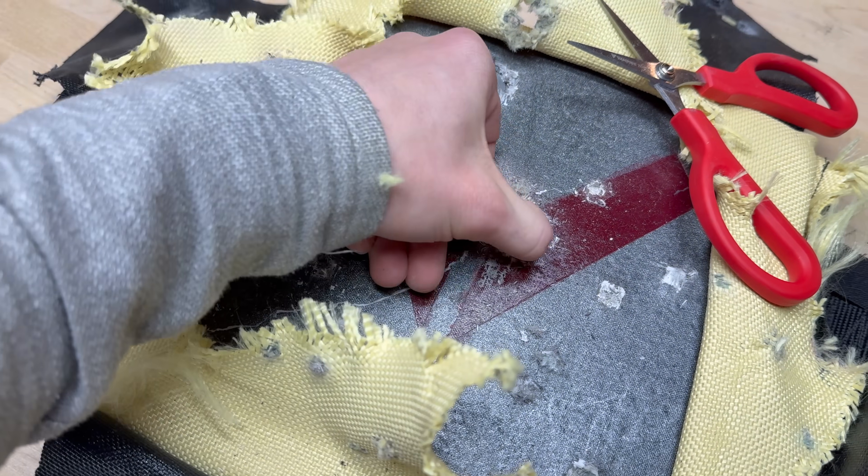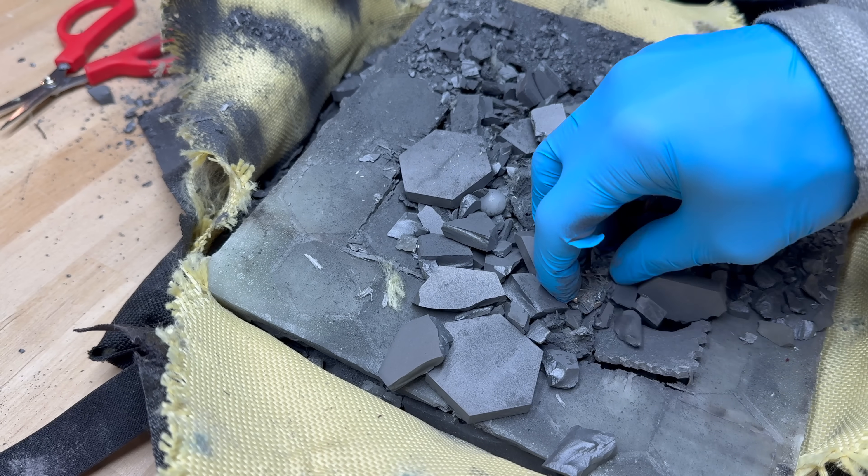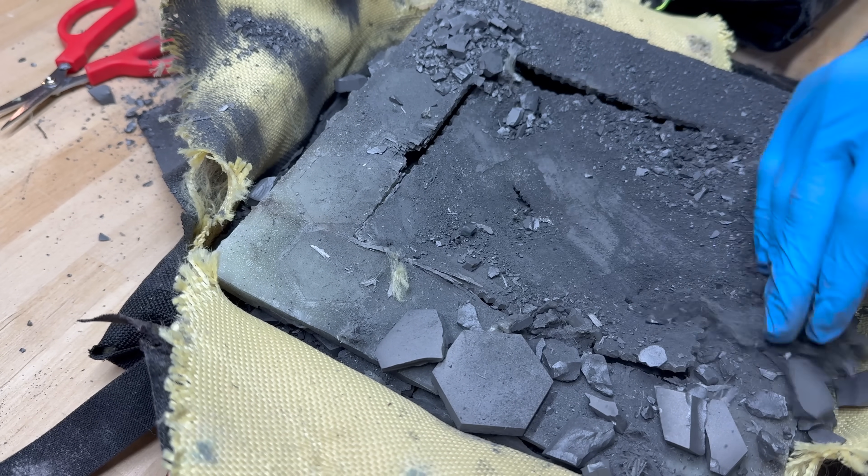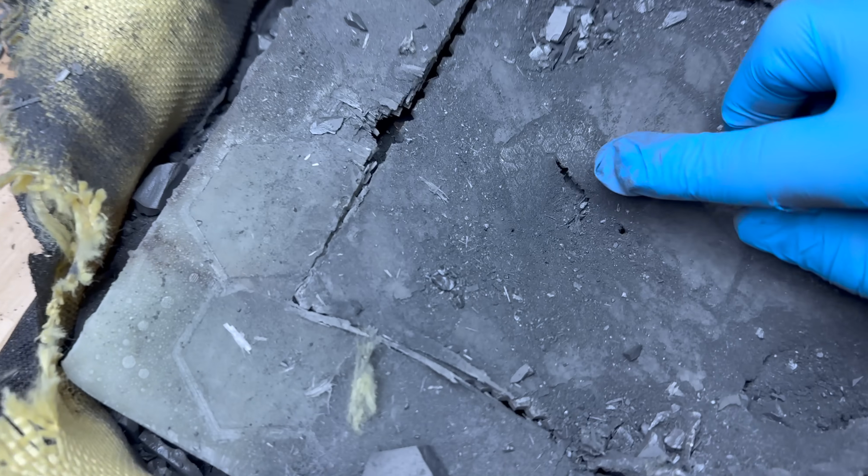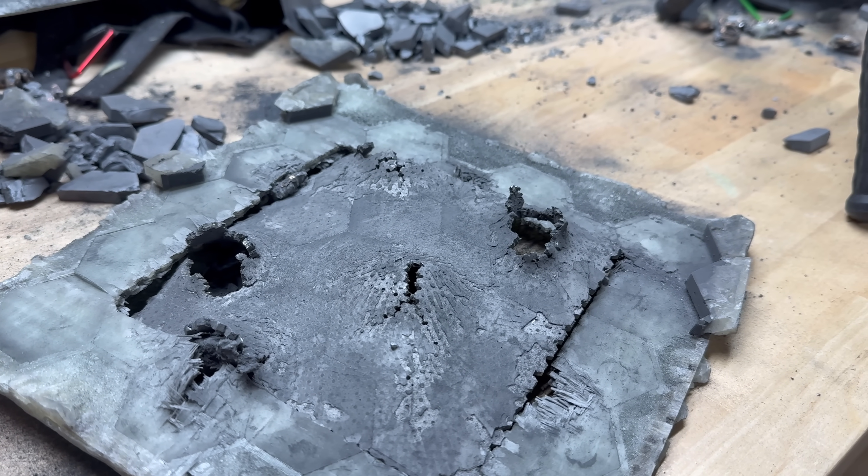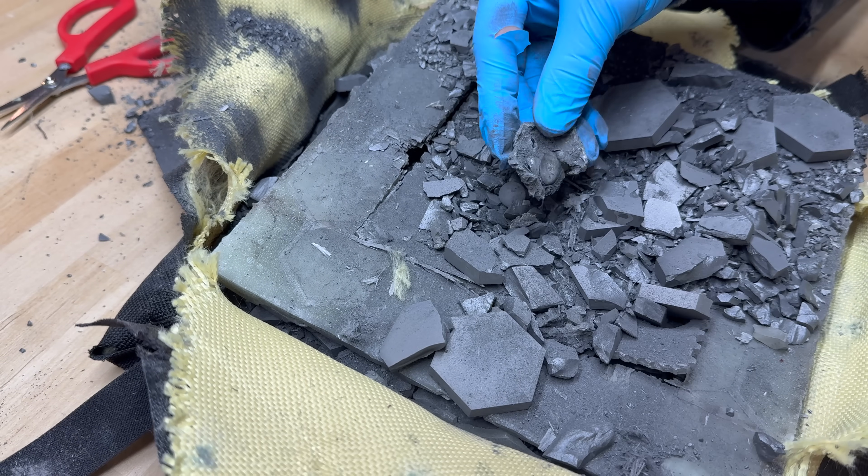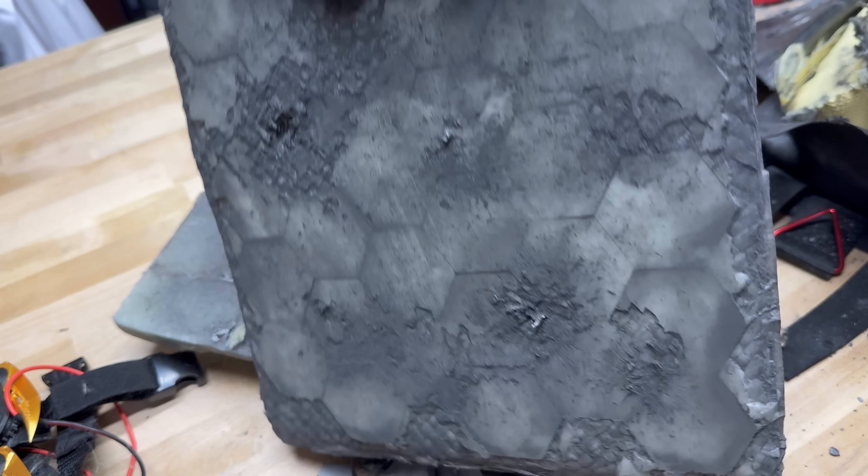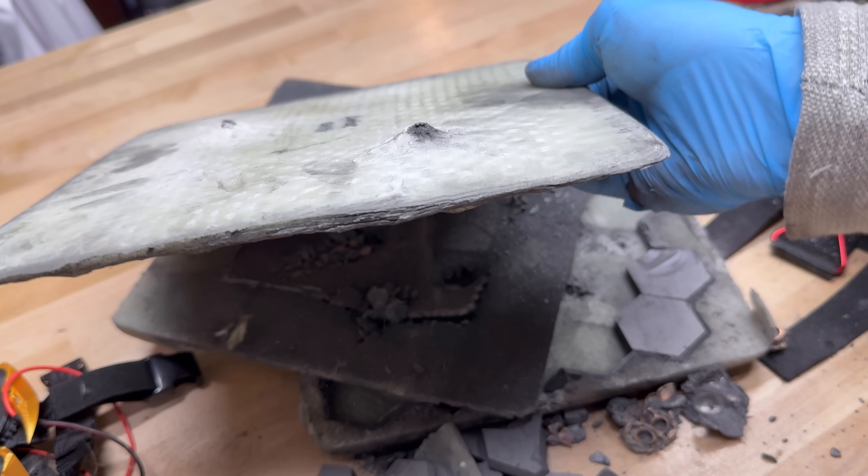Now taking this apart, I didn't realize how damaged these tiles were. And it was still taking those 5.56 rounds just fine. Which is incredible. And surprisingly the lattice didn't have nearly as many holes as I expected. You can see how deformed it is. It very much was deflecting and bending as it was being hit. Which is basically what it was for. It's supposed to be an energy sponge. But there are a few notable large holes which I'm certain are the 300 Win Mag as well as those slugs. One of those slugs you can see was totally peeled out and it was sitting there cupped on the surface of that lattice. So the backer panel actually held up surprisingly well. There's very little actual damage here. You can see some of the spread out dust and whatnot from those impacts. But very few rounds actually got all the way through to begin drilling into this back panel. It's still quite flat. The only two serious holes here are from that 300 Win Mag.